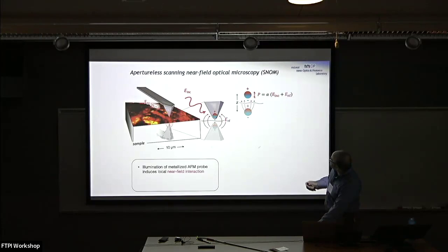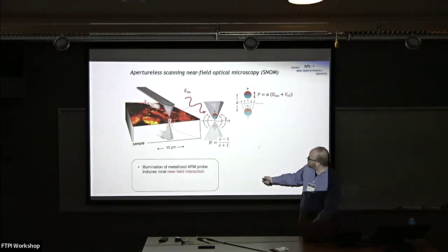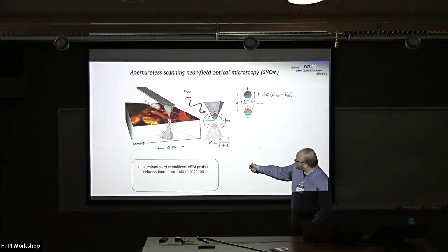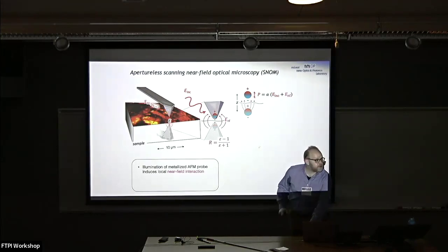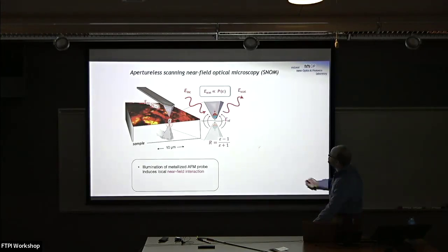And so here's a more mathematical framing of that statement. The polarization of our probe is going to be proportional to how much we illuminate, but it's also going to carry a response to these electrostatic mirrors. And the strength of this image dipole is somehow going to be related to the optical constants of the material, like maybe the permittivity or the conductivity. Right? This is some reflection coefficient.